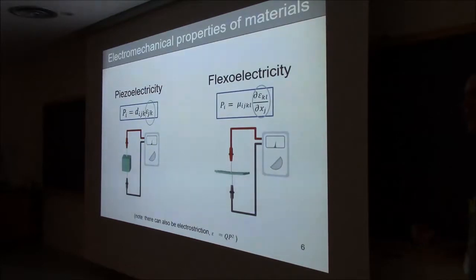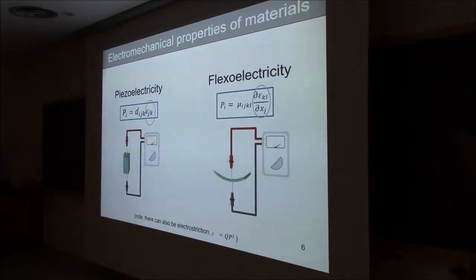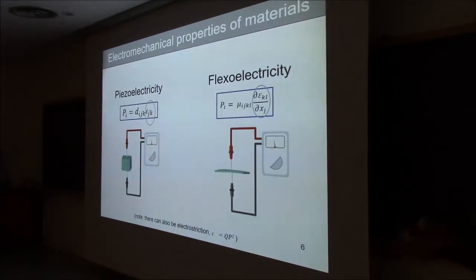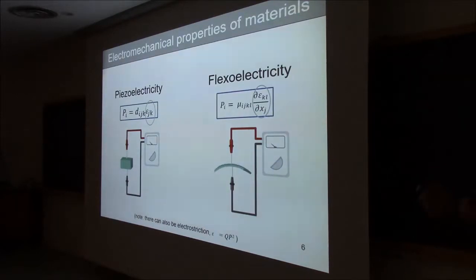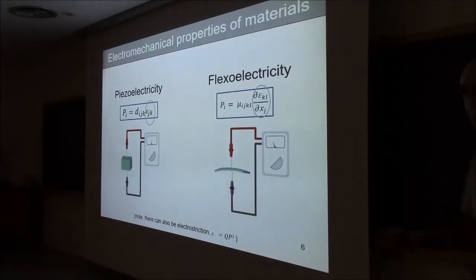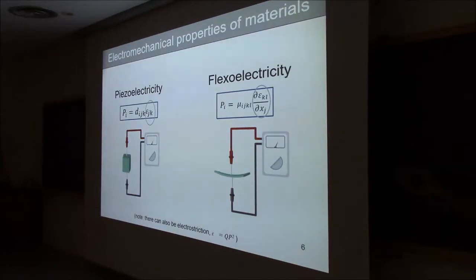I don't really mention it because it's not a comparable magnitude to these other two, in the sense that there isn't a reverse of electrostriction. So if I apply an electric field to an electrostrictive material, it will stretch. But if I take this material and I compress it, I will not get a polarization. And this is because the material is centrosymmetric to start with, remember, and if I apply the deformation, the polarization doesn't know in which way to go, so the polarization does not even appear. Yeah? Is that more or less clear? Do interrupt me at any point that you feel like you're getting lost.